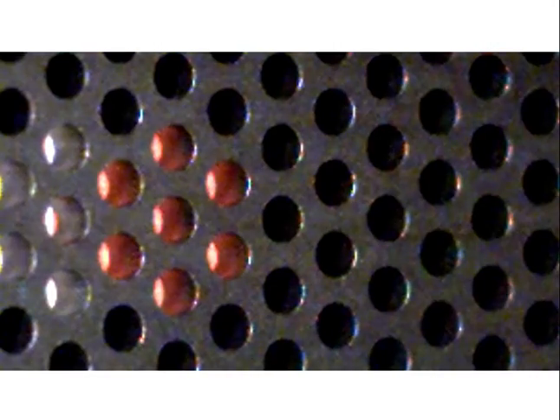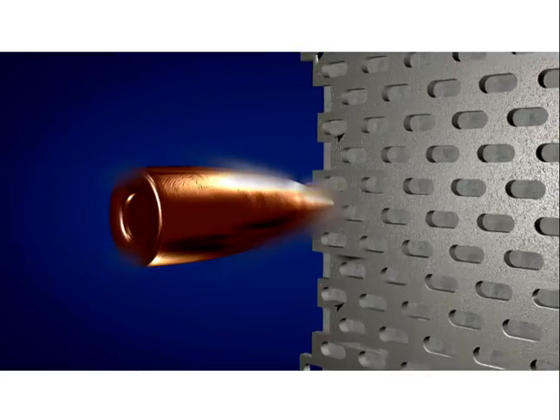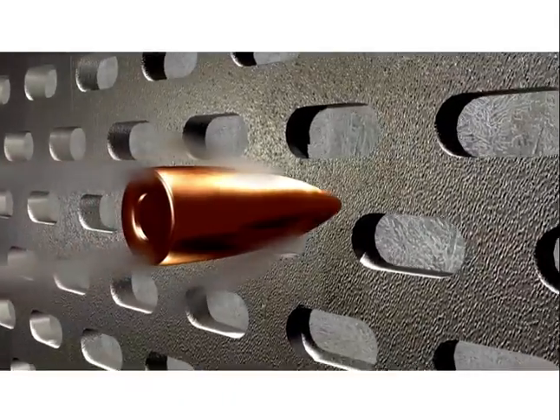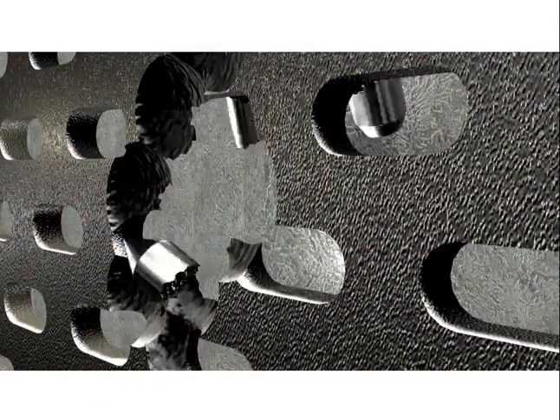I'll show you a movie of actual projectiles being fired at this. You can see the material is not catastrophically fragmented, but the projectile becomes destroyed. There's a cartoon version showing what actually happens. Behind this armor is normal mild steel backing plate which contains the debris. That backing plate is necessary to contain debris but it's not particularly an armor steel. It's a system of armor.